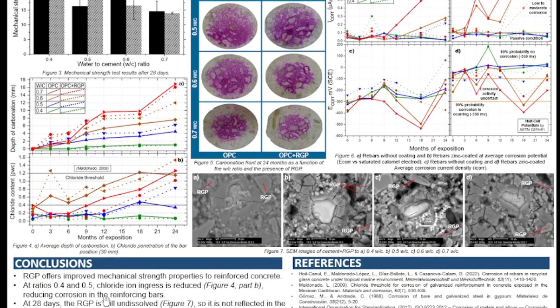Our conclusions are: RGP offers improved mechanical strength properties to reinforced concrete. At ratios 0.4 and 0.5, chloride ion ingress is reduced, as in figure part B, reducing corrosion in the reinforcing rebars. At 28 days, the RGP is still undissolved, so it is not reflected in the mechanical strength. The use of zinc coating in reinforcing steel offers passive protection.